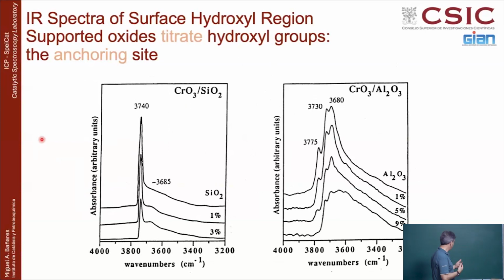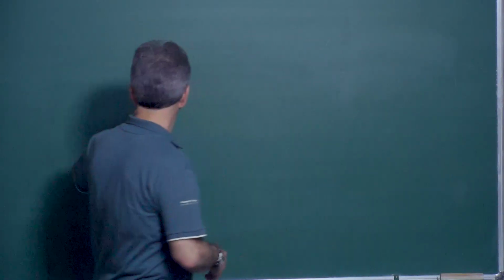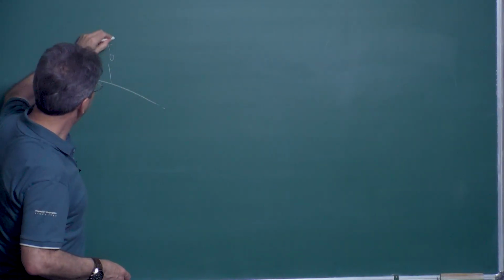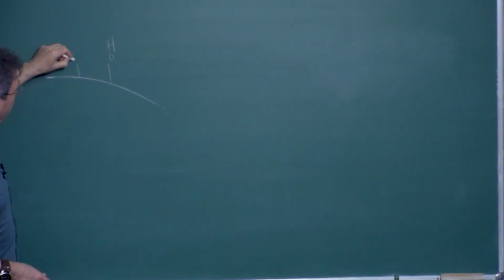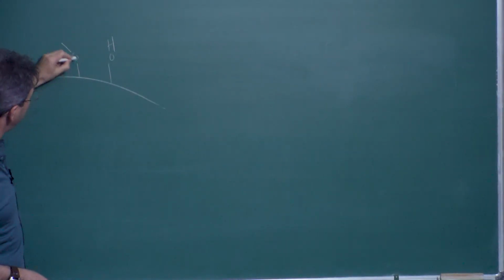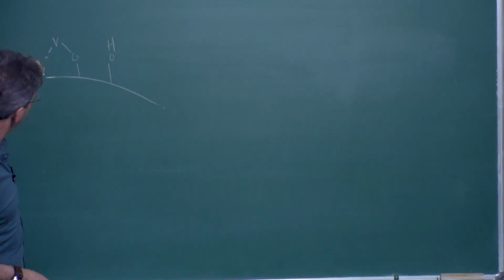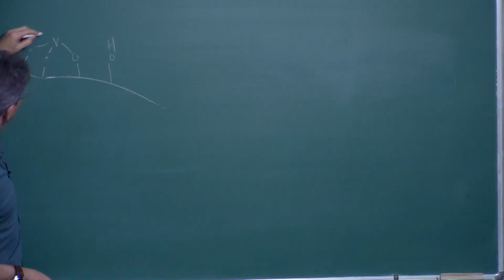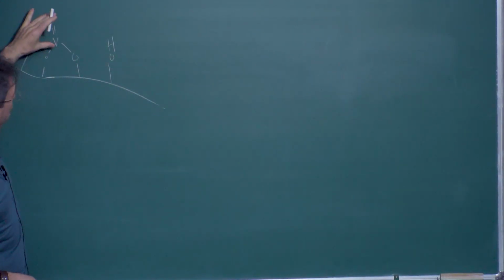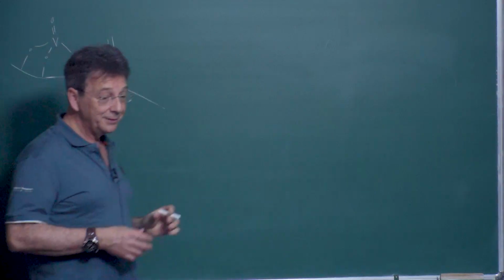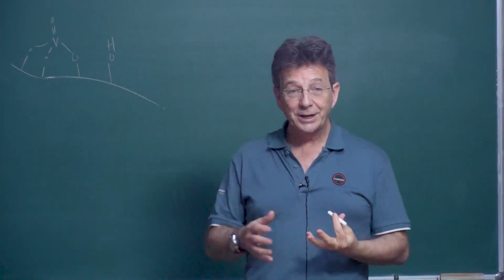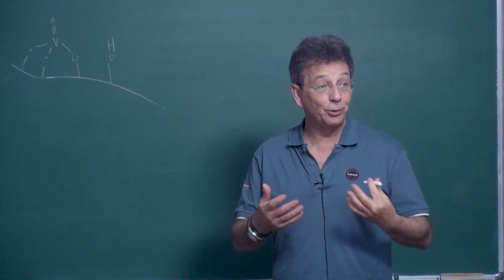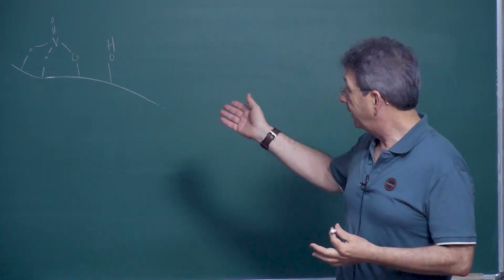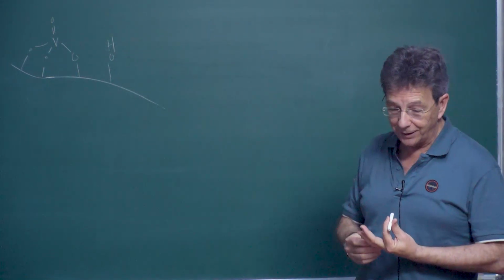Usually when you have a hydroxyl group on the surface, okay, we have a blackboard. So you have the surface, you have a hydroxyl over here, and eventually there is another hydroxyl over here, but if an oxide comes in, it connects with it. Like then you get vanadium, whatever, connecting to other hydroxyls. And basically the oxide that will support is titrating the hydroxyl groups. They stabilize. So if you want to make monolayers, supported oxides, they will typically connect to the hydroxyls at the surface of another support.